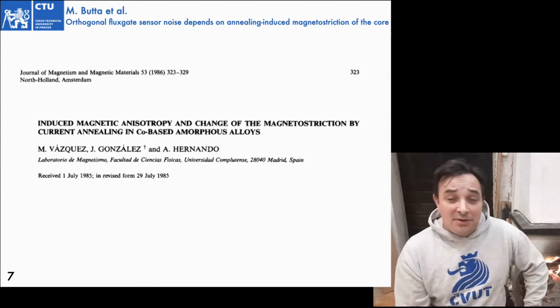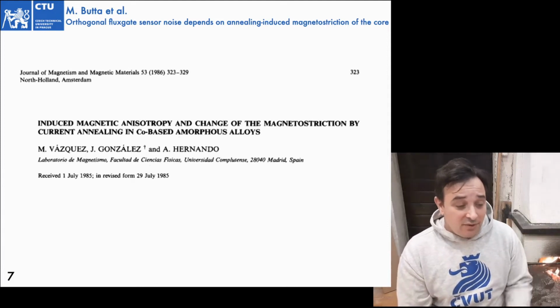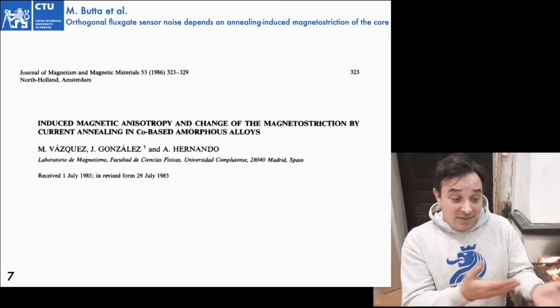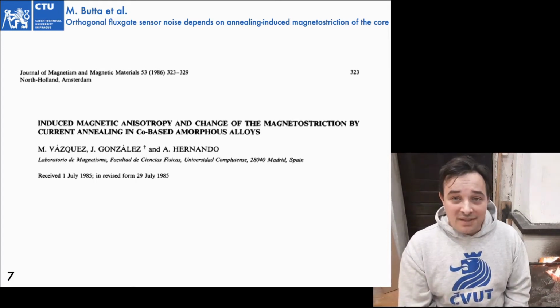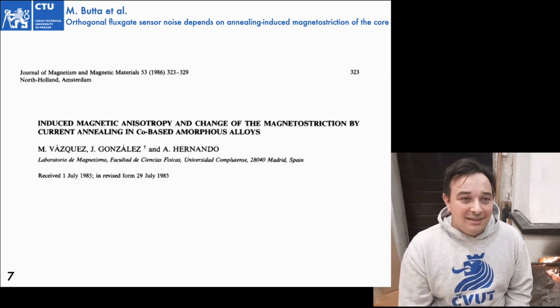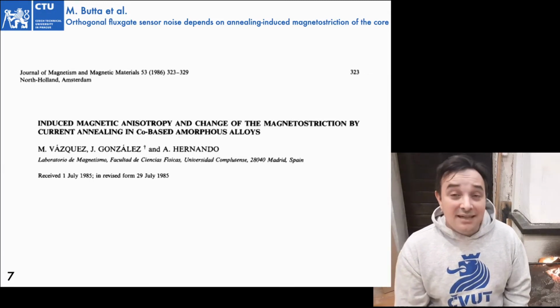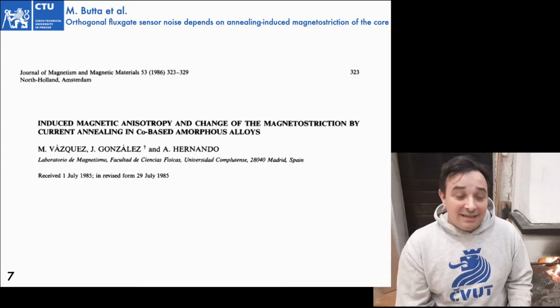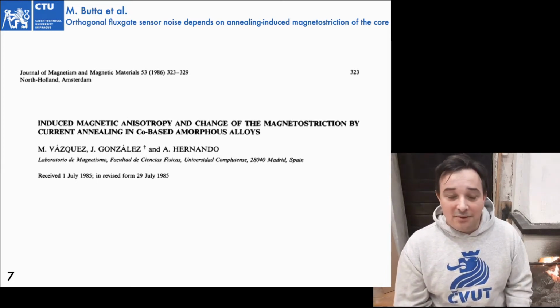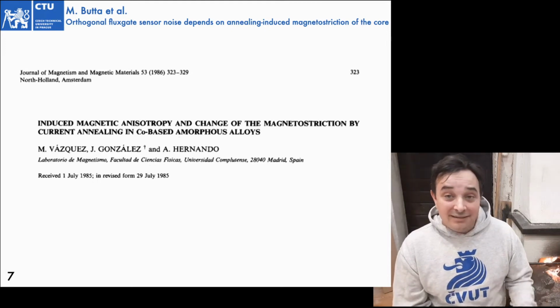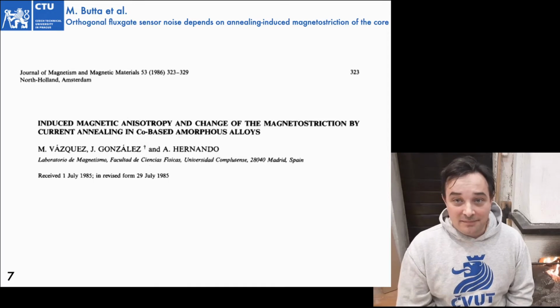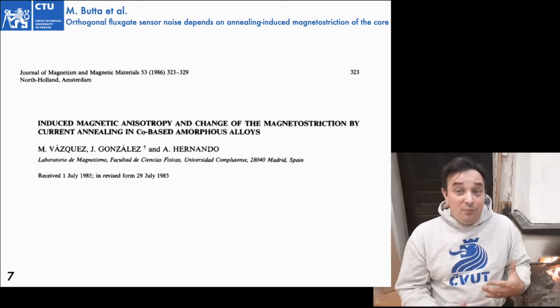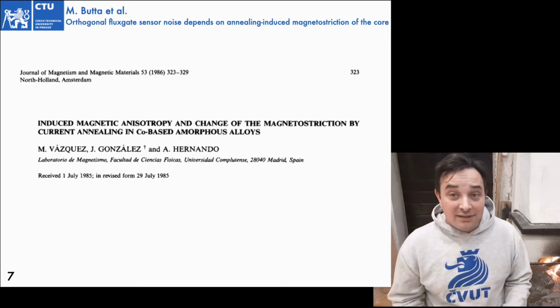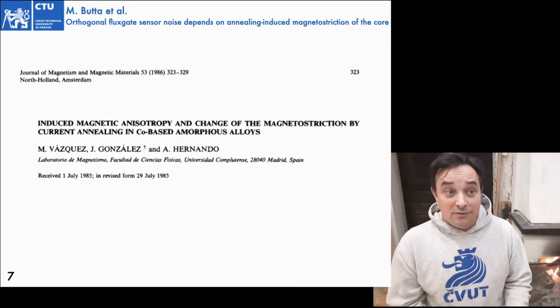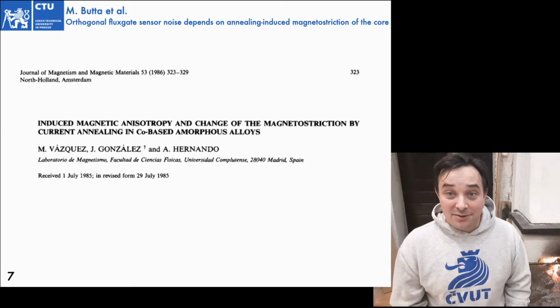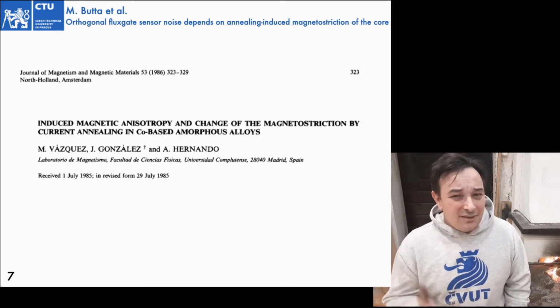And this is a very interesting paper because it shows that in similar alloys, he was working with cobalt, iron, silicon, boron alloys, which are basically the same alloys we use for our sensors. It was showing that the magnetostriction increases with annealing. Well, it gets larger, of course, when you warm up the alloy, but it does also permanently increase every time you perform some annealing. And that is very interesting because that could be the reason why, if you anneal your wire for a longer time, you get a larger noise, because we know that the noise depends on the magnetostriction. So, is that the reason why the noise increases?